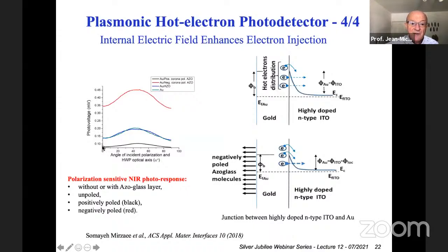It is because when the polarization of the light is inside the plane of the film, it is absorbed. When it is perpendicular to the plane of the film, it is not absorbed. So that polarization sensitivity is exactly this one. So we had the detector at slanted incidence versus the propagation of the light, and we are turning the polarization of the light. When the light is in the P polarization, we have a minimum of absorption of that light because there is a component which is perpendicular to the film.